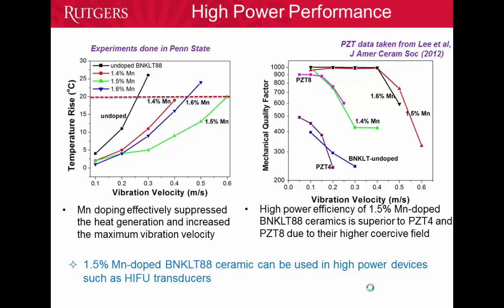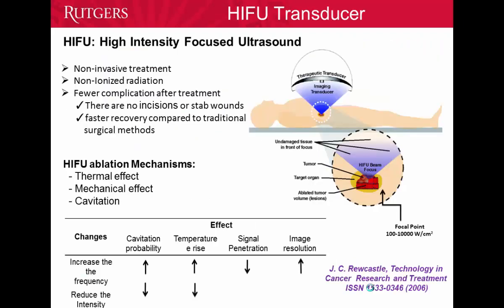And in this plot, you can see that by doping manganese, the stability of the mechanical quality factor is incredibly enhanced, up to 0.45. And for commercial PZT, you can see that the mechanical quality factor decreases rapidly at around 0.15. So we could say that these compositions can be used in high-power devices such as HIFU transducers.